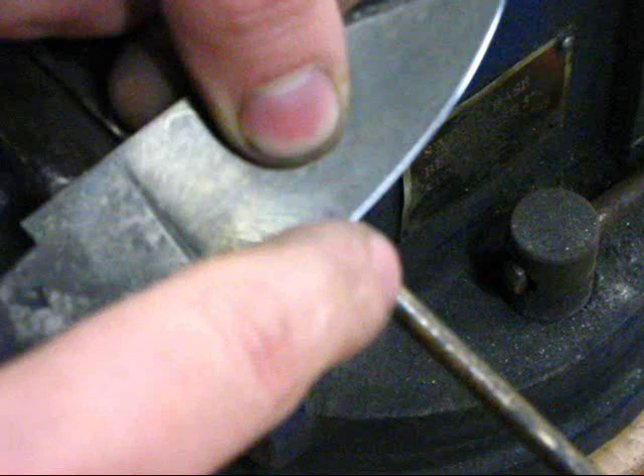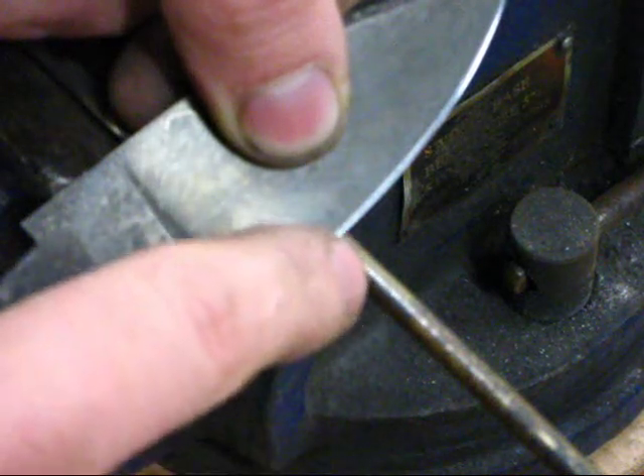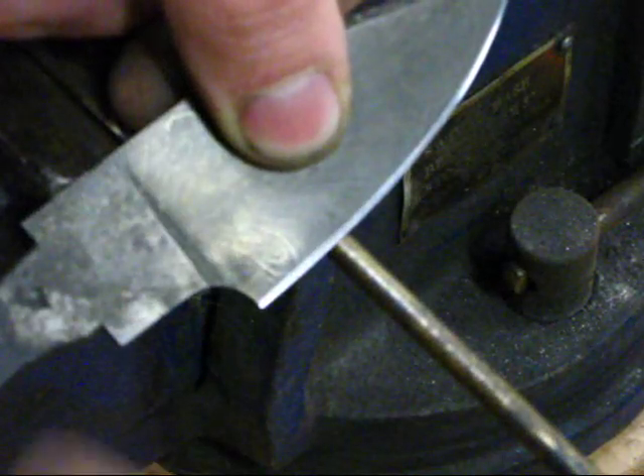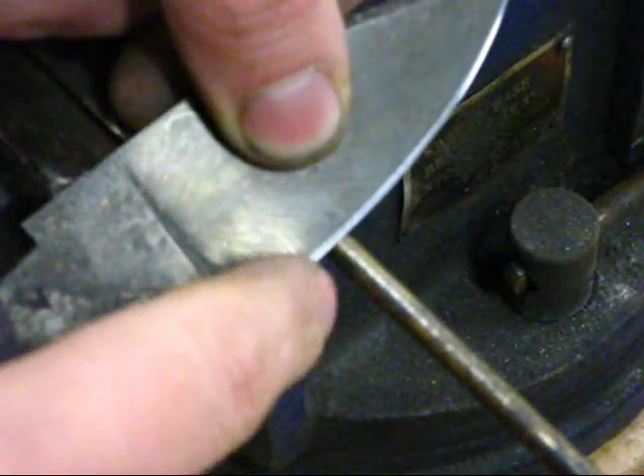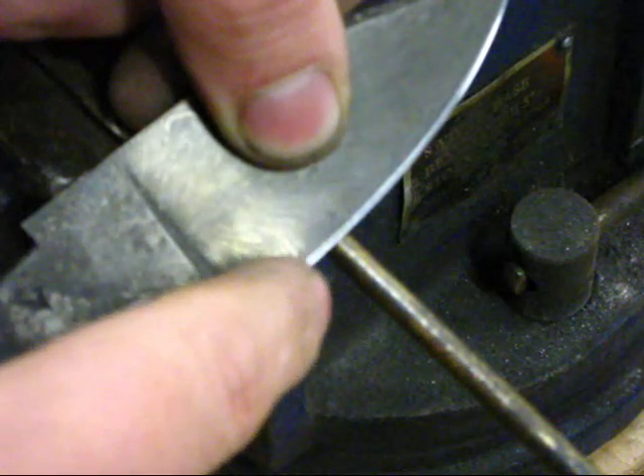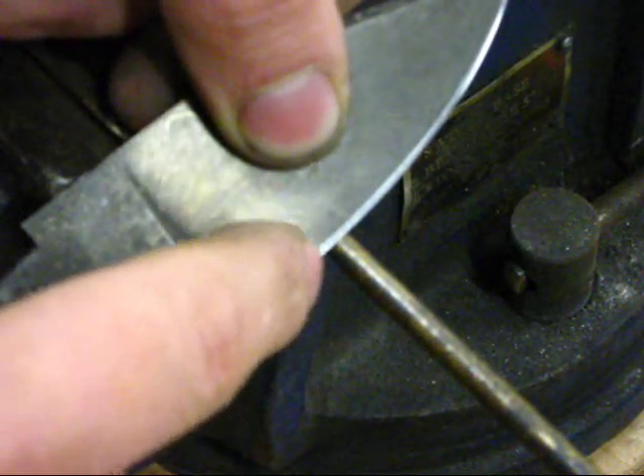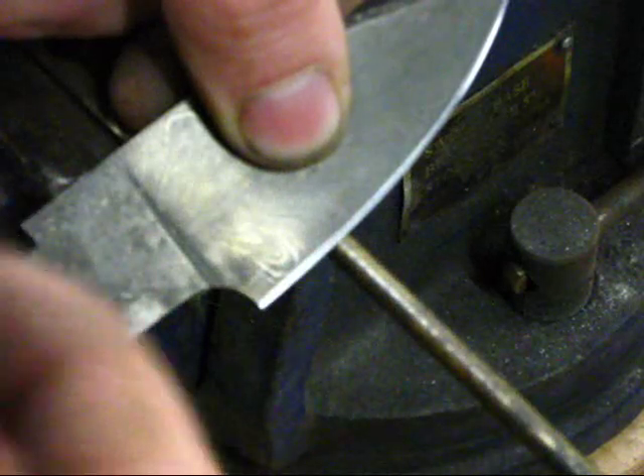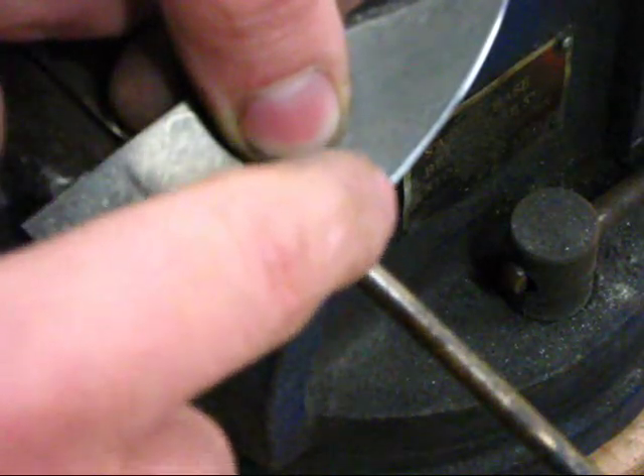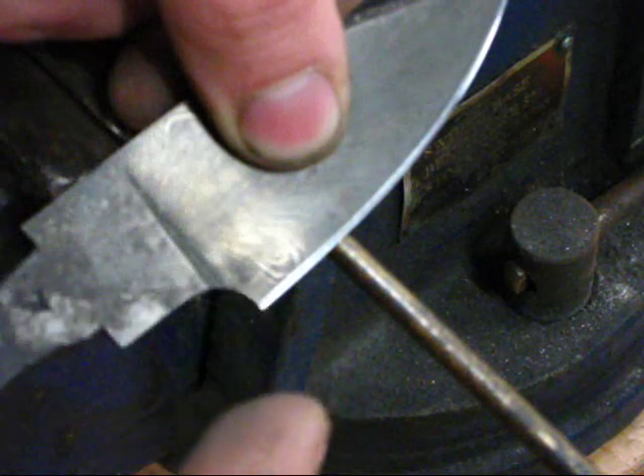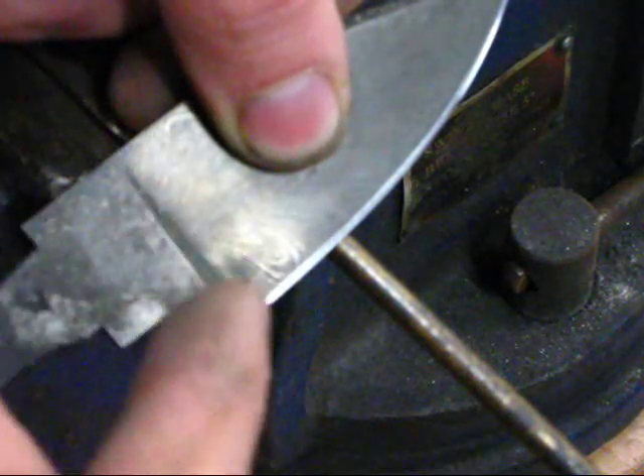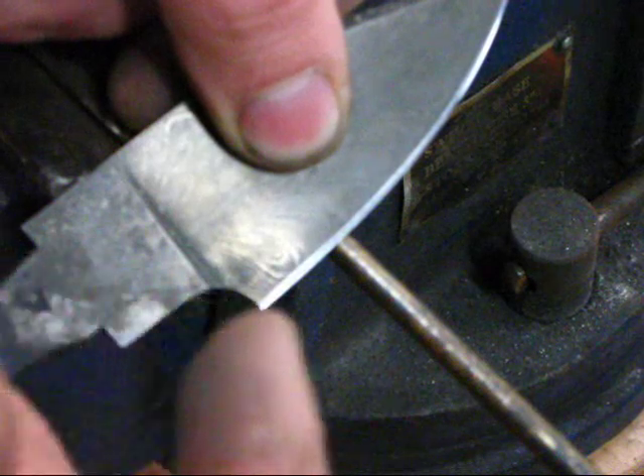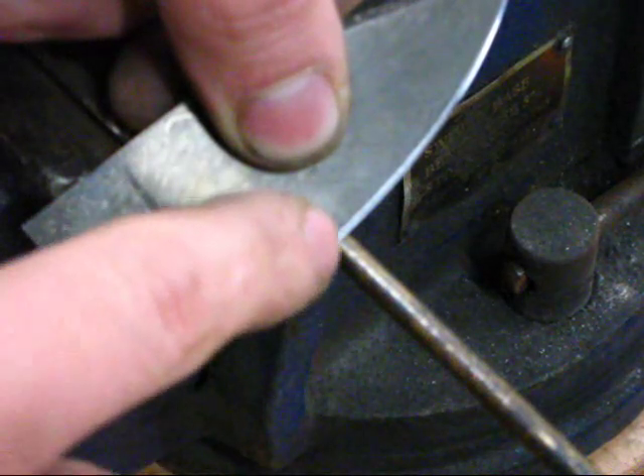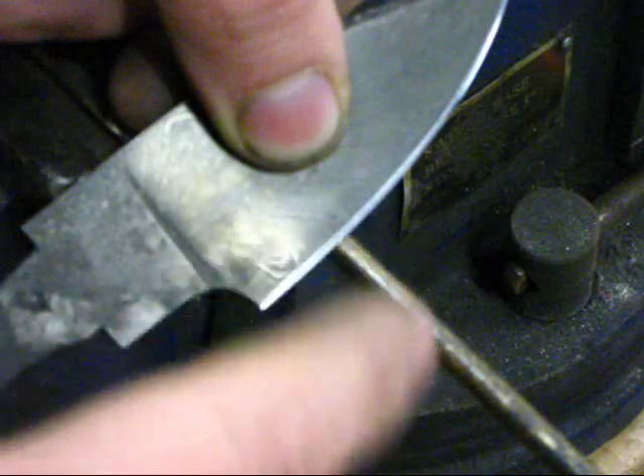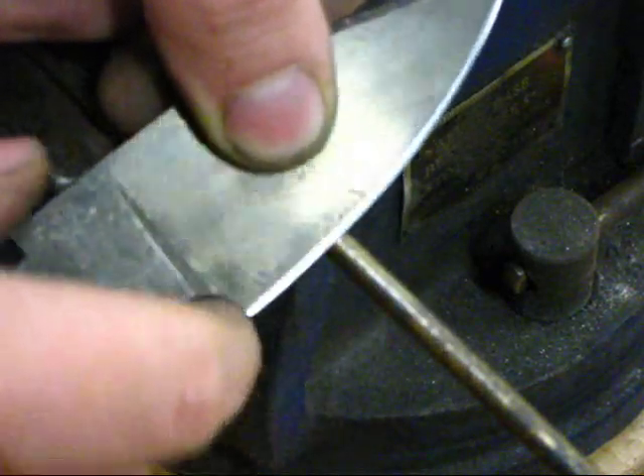If the edge folds over as I draw it across the rod and it doesn't return back to its original position, then that means that the edge has been tempered too much and it's too soft for a good usable edge, and it won't hold a good edge, which is obviously something that you want in a knife, a knife that holds a very good edge. In that case, I have to go back through, renormalize, reharden, and retemper the knife, this time at a slightly lower temperature than I did previously, and that will give me a slightly harder edge that hopefully shouldn't fold when I do the next edge flex test.